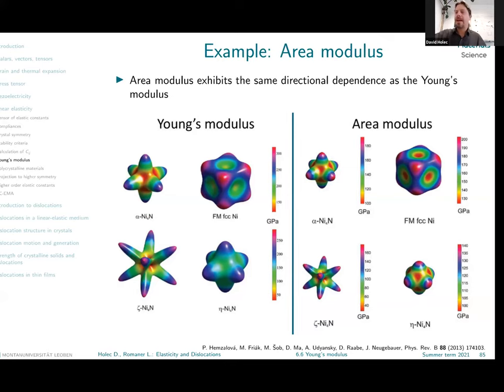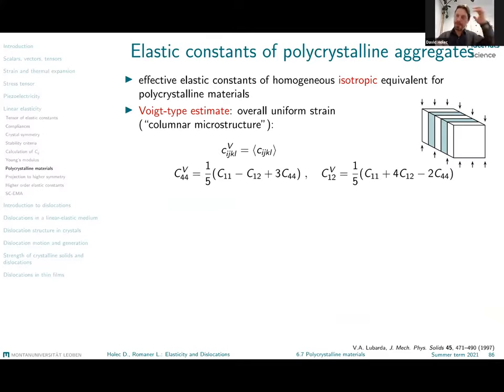Let us briefly come to polycrystalline values. If you look into the literature, very often people state that they calculated polycrystalline mechanical properties, atomistic people like me. What are those? Of course, we can't calculate polycrystalline materials. What we can calculate is a single crystal and then do a certain averaging of these directional dependencies of Young's moduli. There are two types of such averages.